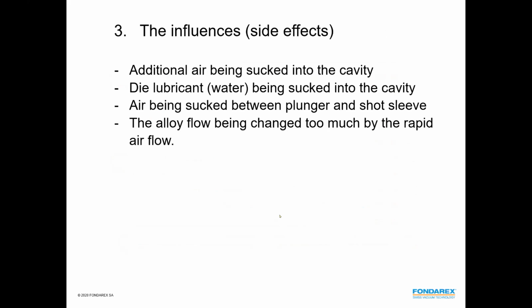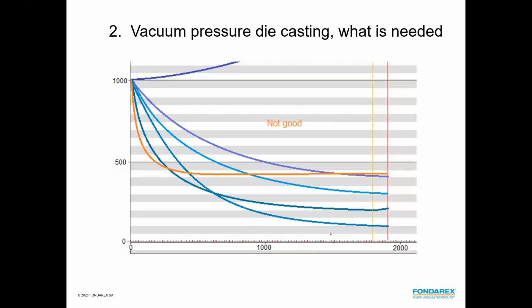So if we go a little bit further, vacuum has a lot of influences, and this is where the key point is. We have to handle all the influences which are creating those different curves. As we can see here, we have one curve which I put in orange, which I would consider is not a good curve. Why? Because we can see it comes quickly down and somehow we don't get any further. It's the proof of probably a big leak somewhere. We cannot get a better vacuum in a mold because there is too much leak. So we'd rather have a curve which comes down like this and is still going down all the way until the filling phase is done.